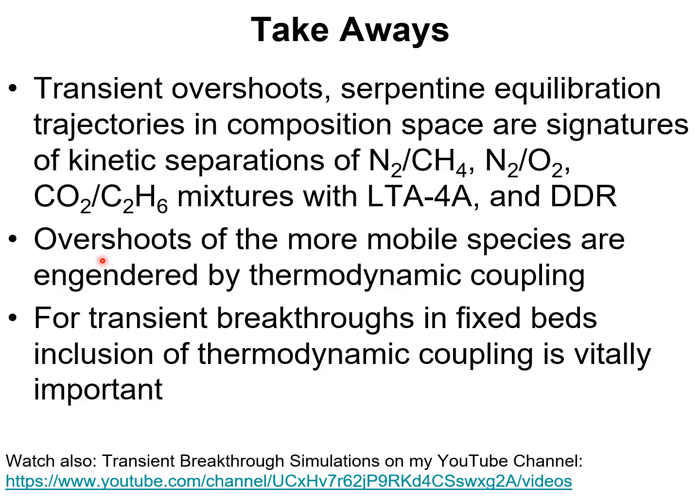The transient overshoot of the more mobile species is engendered by thermodynamic coupling effects that are described by a two-dimensional matrix of thermodynamic correction factors.